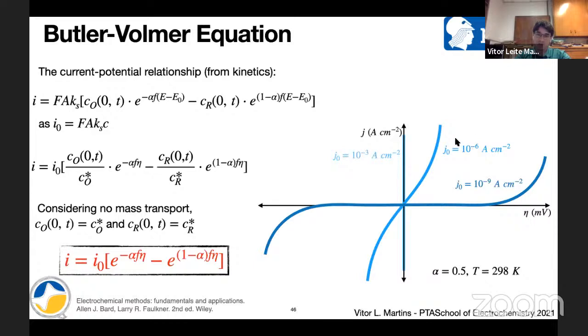And then if I have an intermediate value for the exchange current, we have a profile like that. And if I have a very large one, it means that the resistance of this charge transfer is so low that we don't have any change in potential during this flow of electrons, right? So this will be like the ideal case of the non-polarizable electrode, as I showed you before. So this is a very large exchange current.